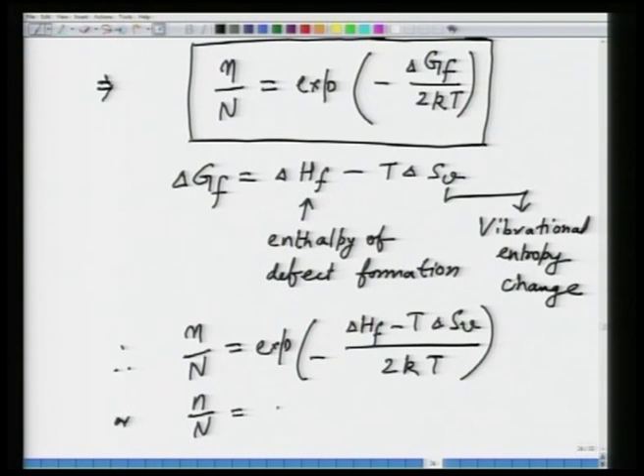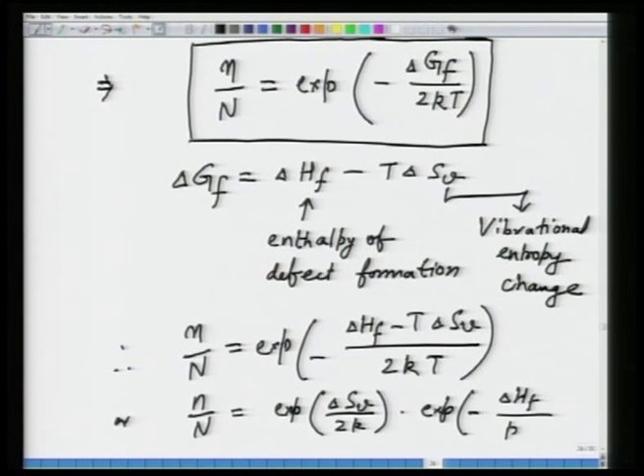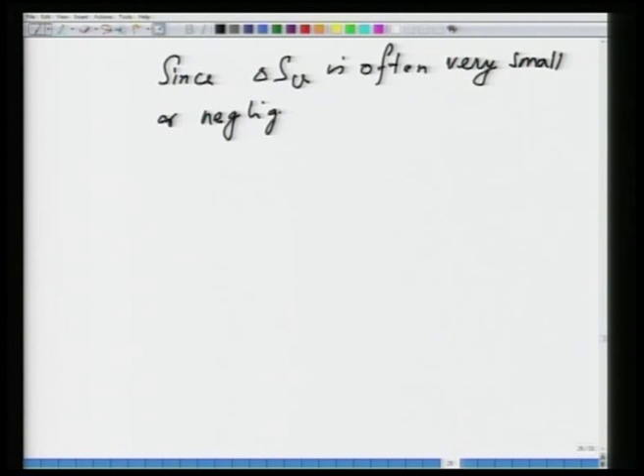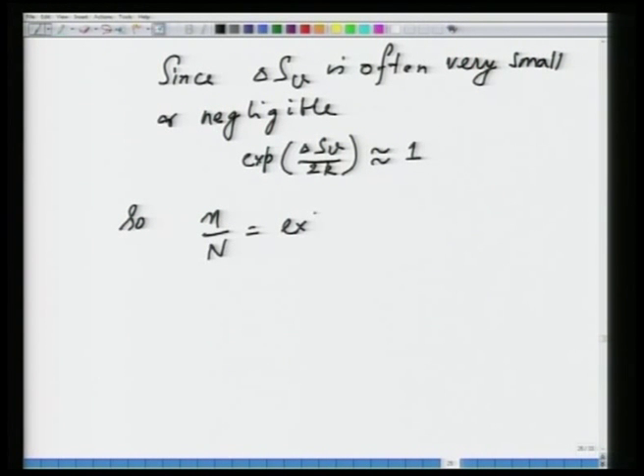equal to exponential of delta S v by 2 k multiplied by exponential of minus delta H f by 2 k T. Now, in most cases what happens is this entropy change is very small. So, this term is often neglected. Since delta S v is often very small or negligible, exponential of delta S v divided by 2 k is almost equal to 1. So, n by N is equal to exponential of minus delta H f by 2 k T.